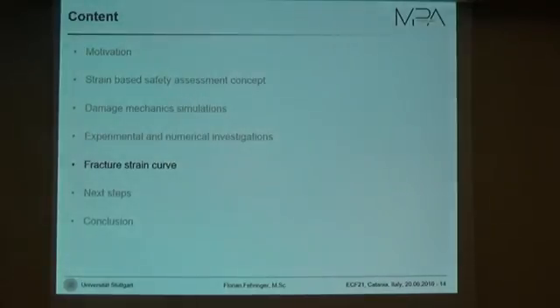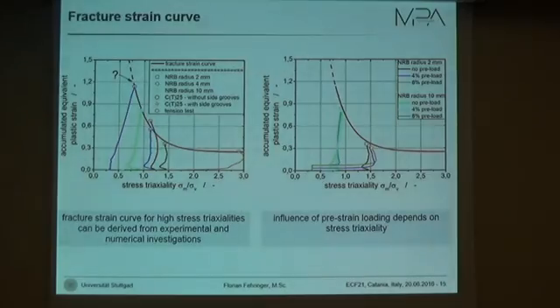Okay, so all the experiments I showed before we used to derive a fracture strain curve. Why is it a fracture strain curve and not a limit strain curve? Because it only contains stress triaxiality and much more importantly, it doesn't contain any safety factors. So the fracture strain curve shows us the accumulated equivalent plastic strain at crack initiation as a function of the stress triaxiality. And as you can see, for high stress triaxiality values, we can fit the curve with a decreasing deformation capability with an increasing stress triaxiality.